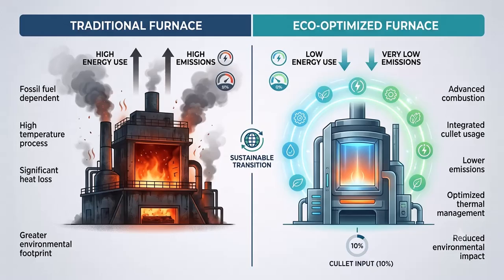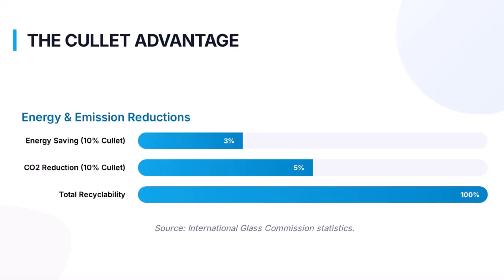Recycling also saves a massive amount of energy. For every 10% of recycled cullet we add to the furnace, we reduce energy consumption by 3% and CO2 emissions by 5%. Because cullet melts at a lower temperature than raw sand, the furnace doesn't have to work as hard, making the process significantly greener and more cost-effective.